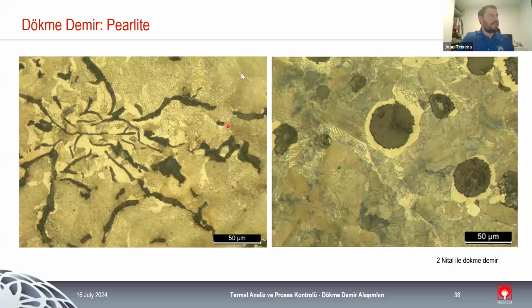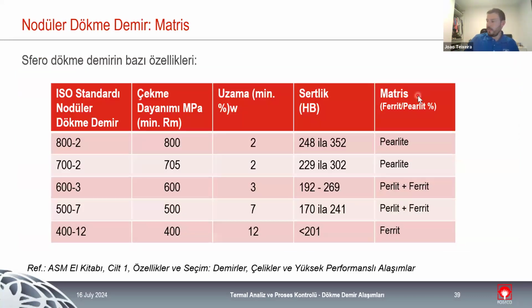And again, this is a sample analysis with pearlite. Normally we need to etch it with 2% Nital to have this appearance, but you can see that we have the graphitic nodules, we have the austenite around the graphitic nodules, so we had a really close eutectic solidification. Both austenite and graphite grow at the same time, so we have a capsule of austenite around the graphitic nodule, and you have the pearlitic structure around. And this is just to illustrate the differences in mechanical properties with the different types of matrix that we can achieve.